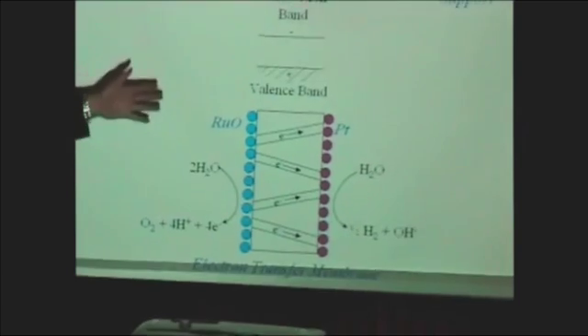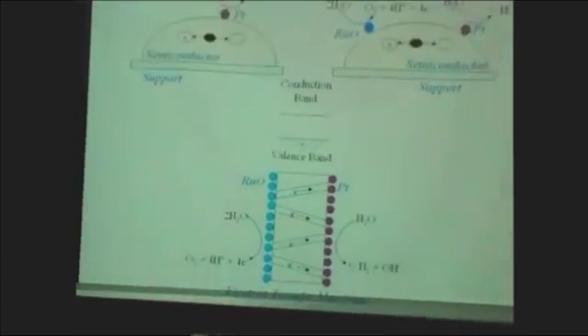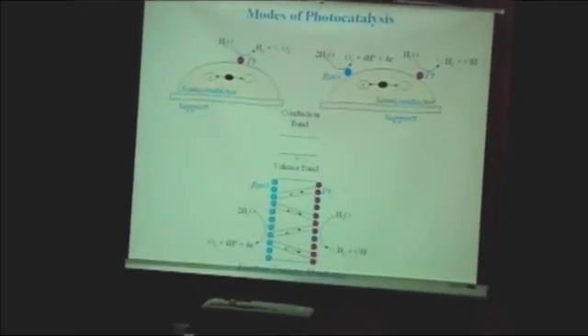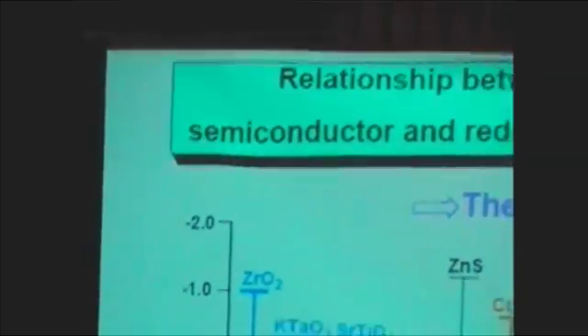The problem with all these types of catalysts is that the reaction is very slow. We have been trying to run this reaction for the last 5 or 6 years, and we have never succeeded. We always produce a very small amount of hydrogen, really beyond our instrumentation ability. It's within the experimental error of our GC. And if you look at the rate of the best catalyst for hydrogen production, in fact, this is the best type of catalyst.